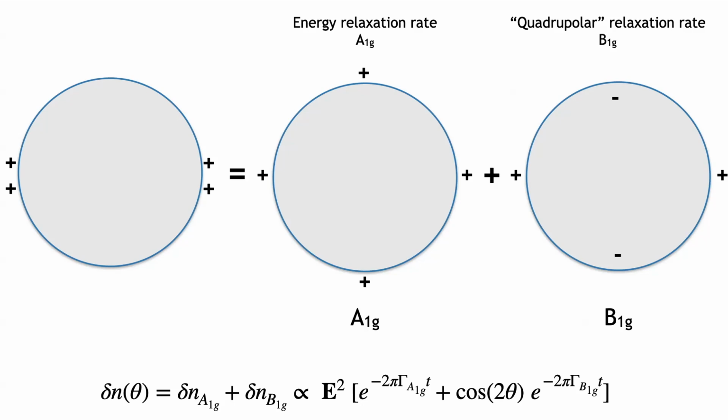So momentum is not relevant. Momentum loss is not relevant, but energy loss is relevant, right? So how does energy leave an electronic system? Well, impurities don't matter because they're generally completely elastic. Electron-electron interactions don't matter. Two electrons can scatter off of each other, but they just exchange momentum, let's say, and they leave the energy still in the electronic system. It's just acoustic phonons, low energies, that are the only source to take energy out of the electronic system and put it into some kind of bath.